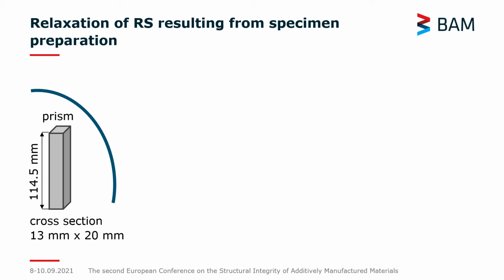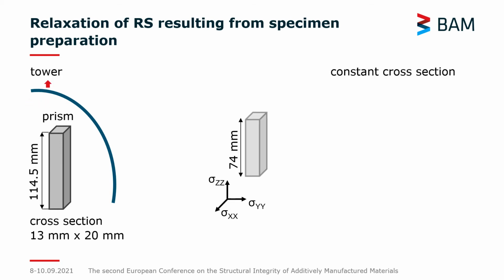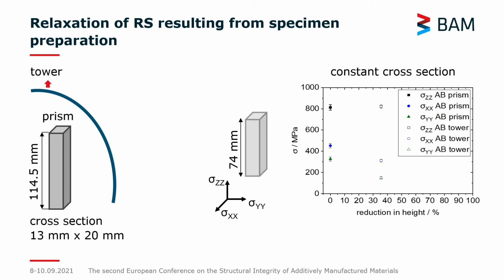Starting with the relaxation of residual stresses resulting from specimen preparation, we are looking at how the residual stress ranges change when extracting different geometries from this as-built prism. So we start off with a tower geometry, which is a geometry that is subsequently used to machine tensile samples. We keep a constant cross-section, but we reduce the height. What does it mean for our residual stress ranges? Again, the stress range is the delta between the maximum tensile residual stress and maximum compressive residual stress.